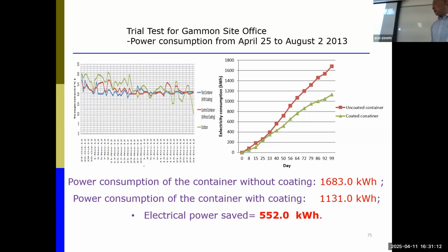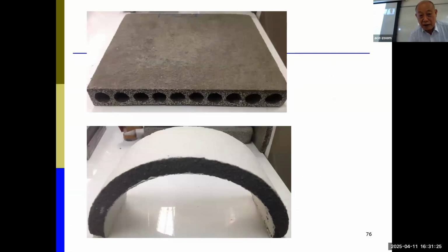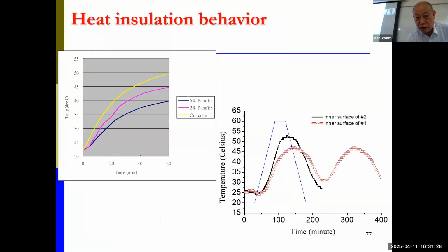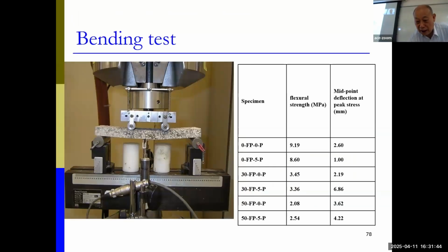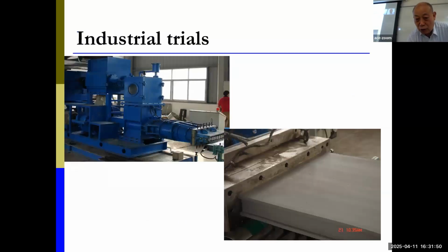For about 3 months, you can see the coating saved about 552 kilowatt hours. That's quite good, the saving for that. And then we developed this kind of extruded material, and we add PCM. You can see you can reduce the temperature difference between the internal and external. And also we have good bending strength, more than 2 megapascal.